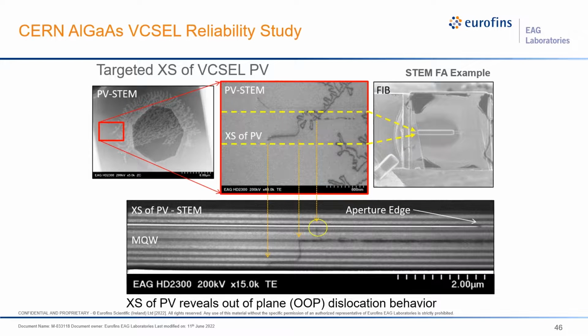Looking more closely at this region from the left side of the plan view image in the previous slide, the upper center image, the red box, shows a small section of the DLD network. That portion of the sample was then cut out with a focused ion beam and imaged in cross-section, shown across the bottom of the slide. The edge of the aperture is at the extreme right of the image. The DLD network can be seen in the red box above it. It can be traced to the corresponding features in the cross-section image below it. This reveals that the DLD network is mainly in the MQW region, but can also be seen to have propagated into the n-DBR below the active region, displaying an out-of-plane dislocation behavior.